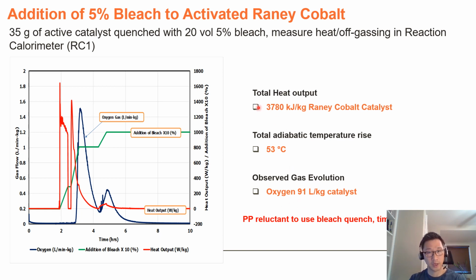So at the end of the reaction, we did the calculations, and we found that the total heat output was about 3,800 kilojoules per kilogram catalyst, which equated to a 53-degree adiabatic temperature rise. Now, a typical plant reactor can handle about a 20-degree adiabatic temperature rise, so this is well in excess of that. What was also very concerning is the gas evolution, 91 liters per kilogram of catalyst. And so once again, if you're charging 20 kilograms of catalyst, you do not want to be producing about 1,800 liters of oxygen when you're trying to do the quench.